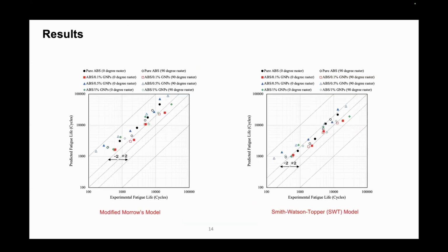Here we can see the results. As we can see, both models over-predicted slightly, for example, the Smith-Watson-Topper slightly over-predicted the results, but the modified Morrow's damage equation over-predicted the results largely. But for the results of Smith-Watson-Topper, the majority of the data fell in between two scatter bands with the factor of plus and minus 2.